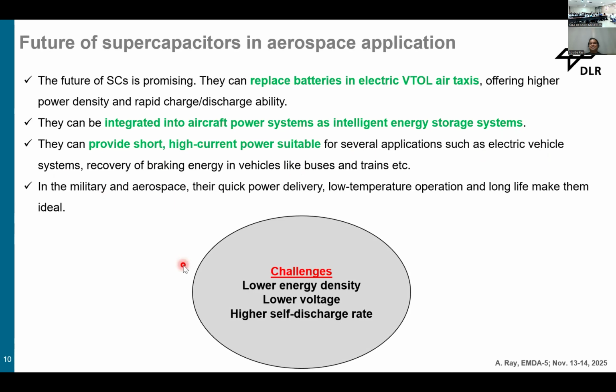And in military and aerospace cases, their quick power delivery, low temperature operation, and long life make them very ideal. But there are also some challenges. The main challenge for supercapacitors is lower energy density. Up to now, for practical real devices it is in the range of 10 to 15 watt hour per kilogram, and lower voltage compared to the battery. It can work below 3 volt. This is still the case for real devices, and I am not talking about any material or small devices at laboratory scale. And there is higher self discharge every day, a 10 to 15% to 20% self discharge rate. So this is the main point that we have to overcome.